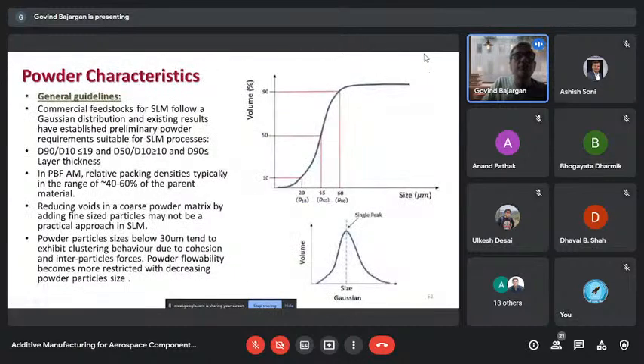The guidelines drawn from these studies are that commercial feedstock for SLM follows a Gaussian distribution, and existing results have established preliminary powder requirements suitable for SLM processes: the D90 by D10 ratio should be less than 19, D50 by D10 should be greater than 10, and 90% of the particles should have a diameter less than the thickness of the layer. So this is the criteria which has evolved. In powder bed fusion AM, relative packing density is generally in the range of 40 to 60%.